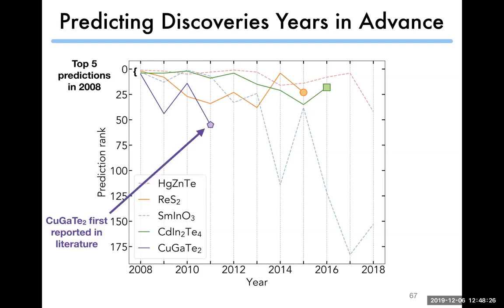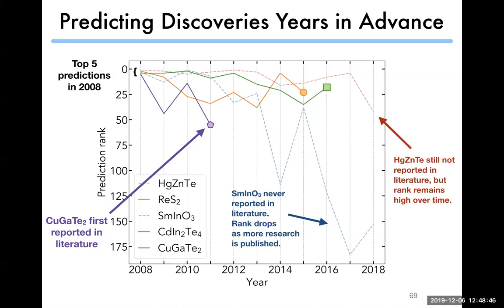So in this case, this copper gallium telluride, it took 4 years or so until a paper that mentions that this is a good thermoelectric material was published. And then the next two took almost 10 years to actually be confirmed as thermoelectrics. And then if we look at these two that were never discovered as thermoelectrics, were never published about, they both contain toxic or rare elements. If you asked an experimental collaborator, you say, I predicted this great thermoelectric, it's mercury zinc telluride, they're not gonna wanna work with that material because it's not really gonna be applied.